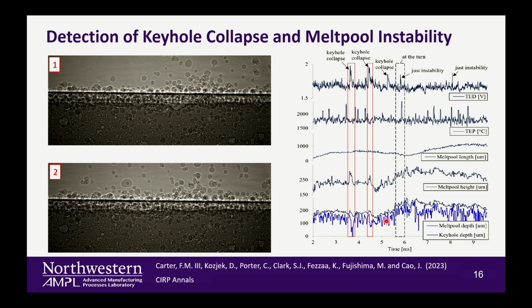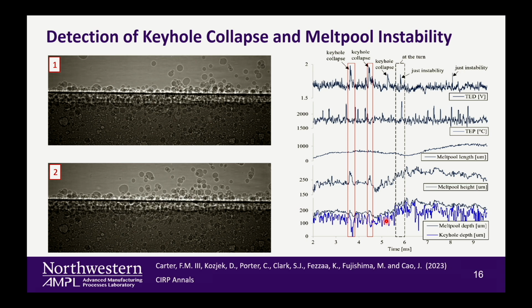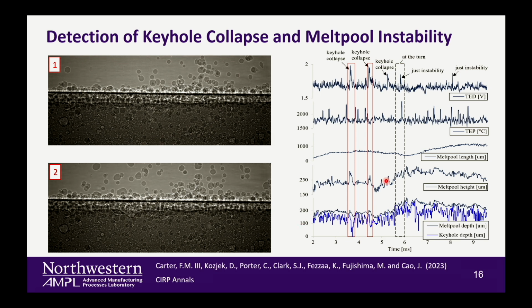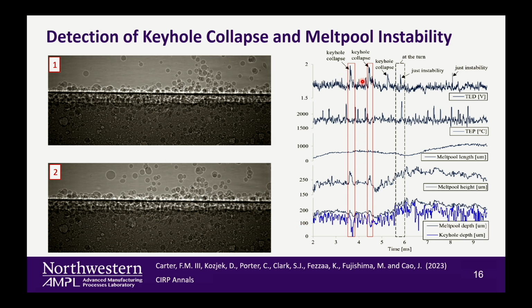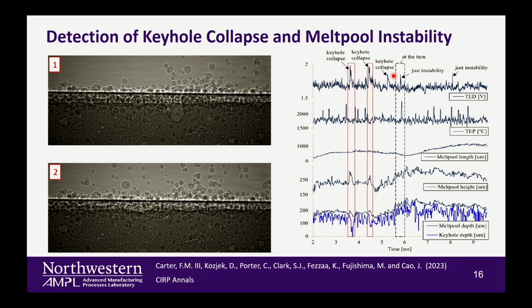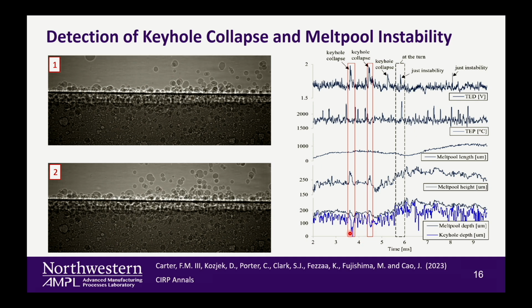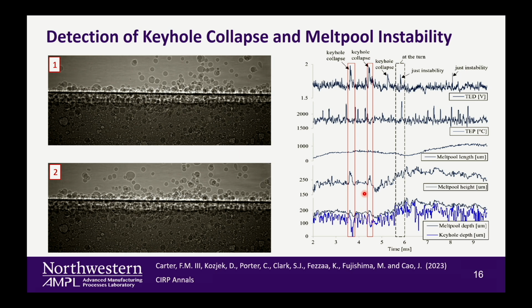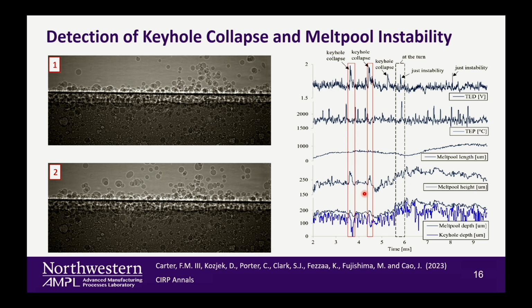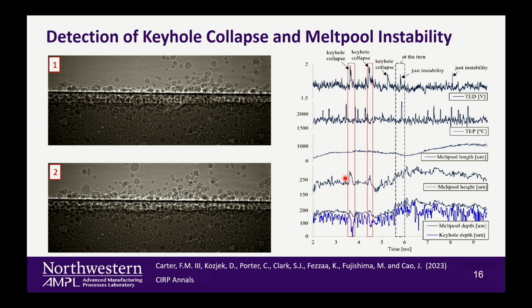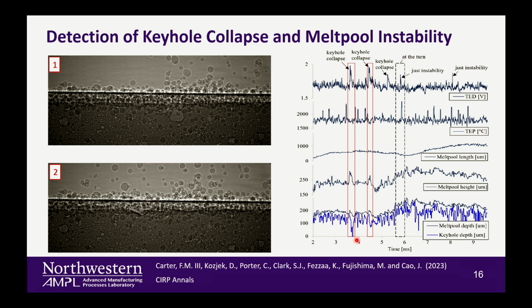And so one of the ways you get porosity is this keyhole, it's not stable, and then it collapses, and therefore it entraps the vacuum and creates this porosity. So what we see is a really good correlation between this so-called TED signal, which is the integration of this energy intensity, and the peak of this corresponds really well to the melt-pool depth collapse. And actually the percentage for this one is 92%. So what this tells us is if we can sense this from the real process, we can assume that maybe a keyhole is likely to be formed, 92% likely, right?